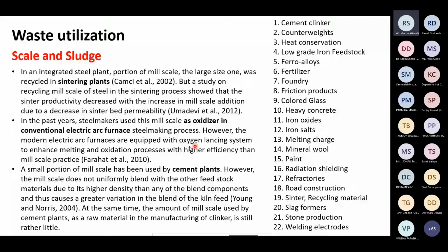A small portion of mill scale has been utilized in cement plants. However, the mill scale does not uniformly blend with the other feedstock. The mill scale is not properly mixed, and then in the steel plant, it fails. It doesn't give the proper result. At the same time, the amount of mill scale used by cement plants as a raw material in the manufacturing of clinker is still very little. It is a very little utilization because it is not giving us the proper results. So these are the various utilization points of the mill scale.